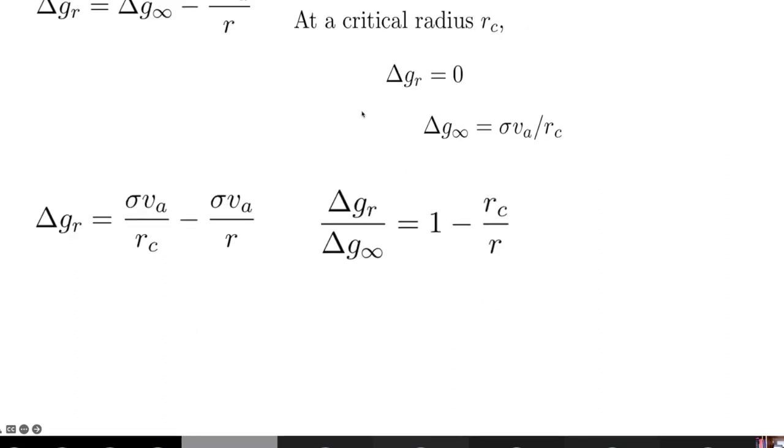And the effect is that if you simply calculate the free energy change from the thermodynamics, this is the maximum, okay? But we have to remove the cost due to the creation of the interface. So this is the only free energy that's actually available to drive the transformation. And if we set this to be equal to zero, then we find a tip radius at which growth is not possible, right? So if I set this to zero, then I get the thermodynamic driving force related to a critical radius below which you cannot get any growth at all.